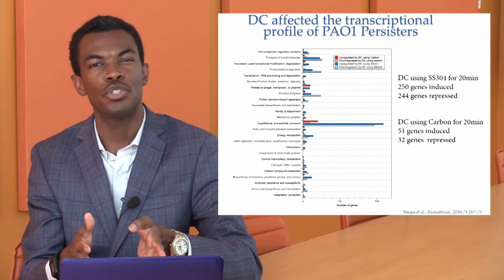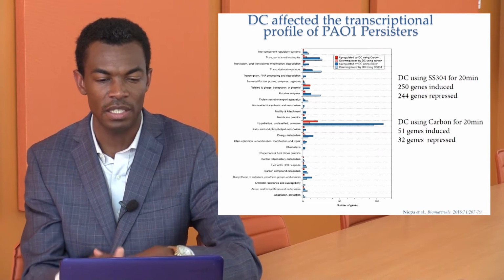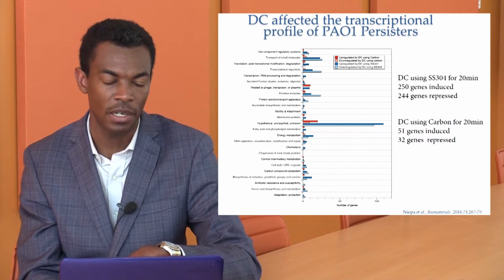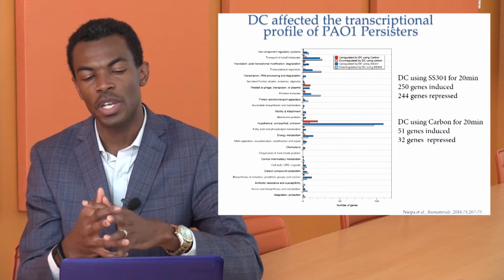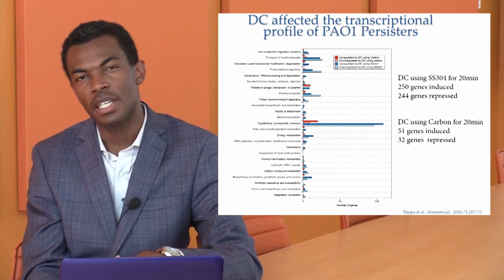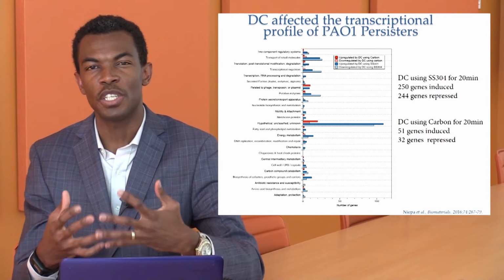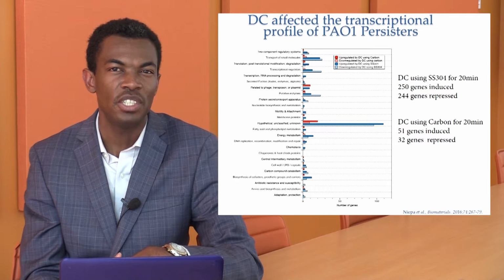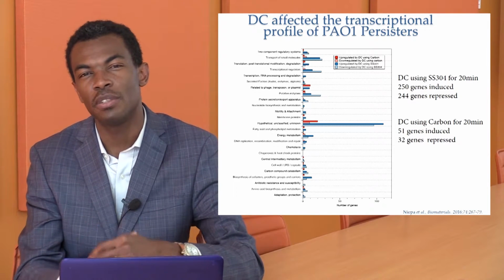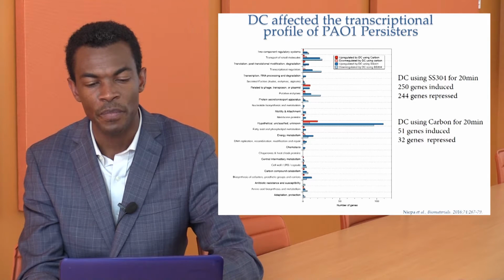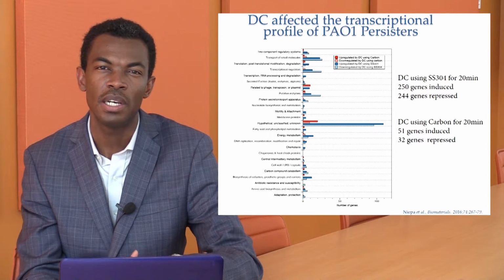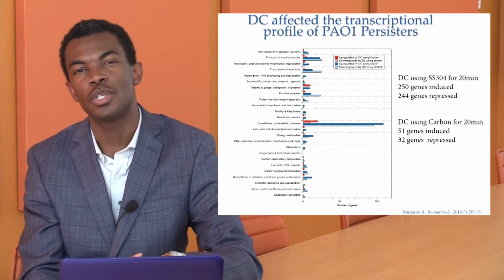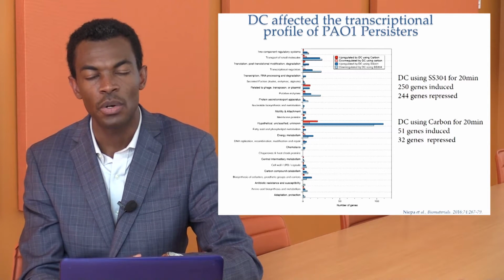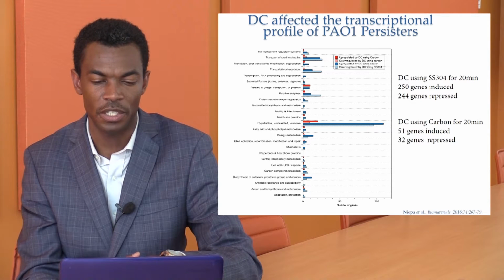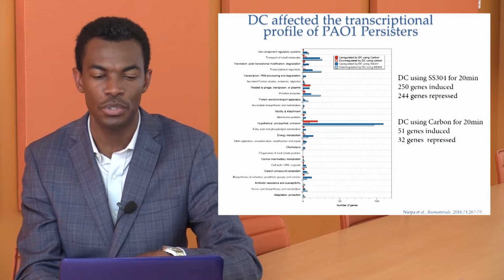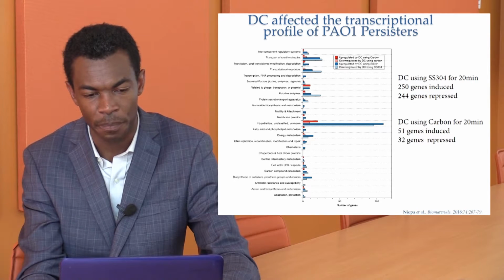So we performed a very short treatment, as we showed previously in this incremental treatment method. Just for 20 minutes, we're able to see that the cells treated with stainless steel electrode were able to express about 250 genes. There were 250 genes that were induced significantly, and 244 genes that were highly repressed. As for the cells treated with carbon electrode in 20 minutes, we had very few genes that were expressed, especially 51 genes that were induced and 32 genes that were repressed.